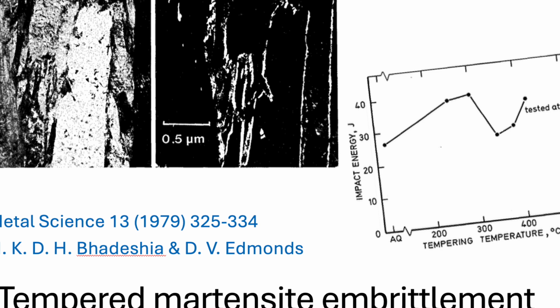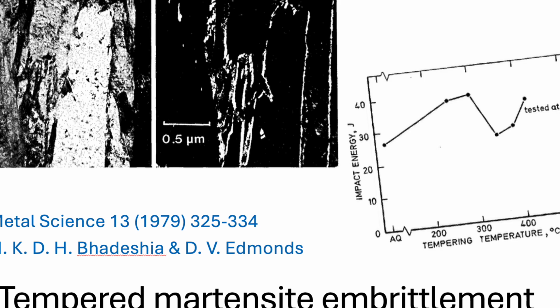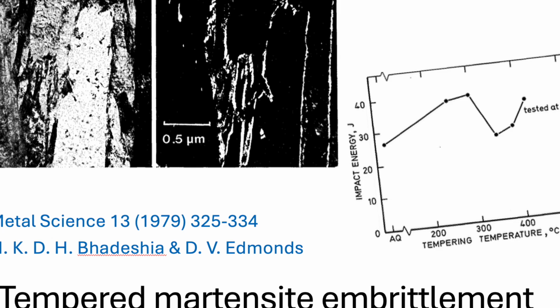Wow. Okay. Now, before this particular research, what was the standard explanation for this dramatic failure? Well, the historical debates had two main camps, but honestly, both were pretty generalized. Some people attributed TME to impurity segregation, where unwanted elements clump together at the boundaries inside the steel, making weak spots. Others blamed a generalized, wide-scale precipitation of carbide phases throughout the structure. But the researchers we're looking at today felt those explanations weren't specific enough. Not specific enough to explain why it happens in that temperature range. Precisely. They couldn't explain the exact temperature dependence.